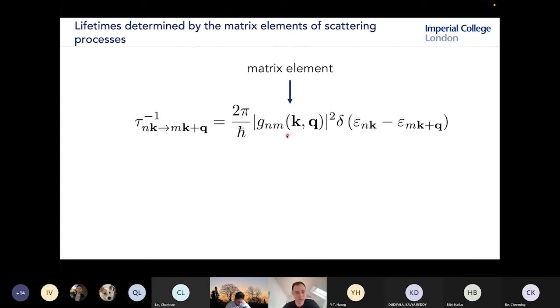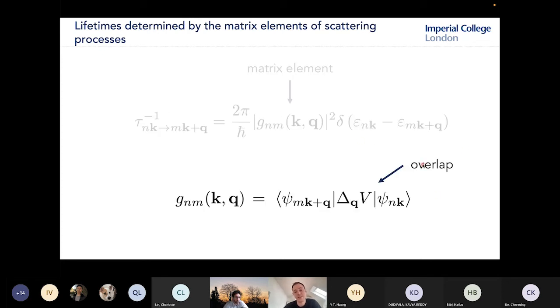I won't go into too much detail, but the gist is that if we want to calculate the partial decay rate from one band at one k-point to another band at another k-point, we have to use Fermi's golden rule, which depends on this matrix element. And this matrix element takes into account the overlap of the initial and final states, and also the perturbation due to a scattering potential. And so the difficulty is calculating these matrix elements.